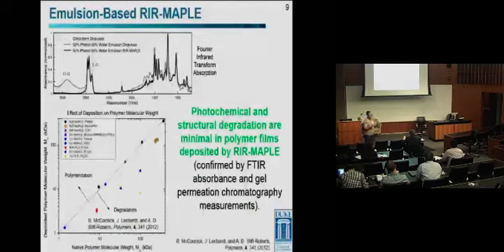So I mentioned, one thing that's nice about this is we don't damage the materials that we're depositing. We've shown this by Fourier transform infrared absorption spectroscopy. In this case, this was a PPV-based polymer, and looking at the infrared absorption shows that there's been no photochemical damage. In this case, this dotted line is showing a drop cast film, where we can see the OH present from the phenol that's missing from the MAPLE film that's deposited. But the other bonds are all very similar to what you get from just a drop cast film that hasn't been through this laser process.